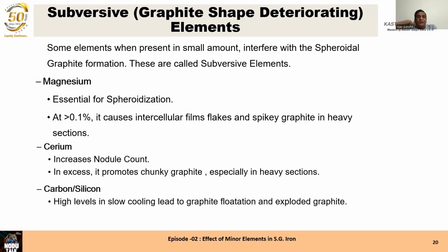Magnesium. Magnesium is very essential for making HDIN for spheroidization. Magnesium, both at the low level as well as the high level, causes subversive graphite. If magnesium is very low, it causes either flake formation or compacted graphite formation, which is also known as vermicular graphite. If magnesium is very high, more than 0.07%, it causes spiky graphite formation, which is not acceptable. If magnesium is higher than 0.1%, it even forms magnesium carbide. So it eventually gets graphitized and you get spiky graphite in HDIN structure. So both low magnesium as well as high magnesium are subversive as far as the graphite shape is concerned, although it's an essential element for making HDIN.